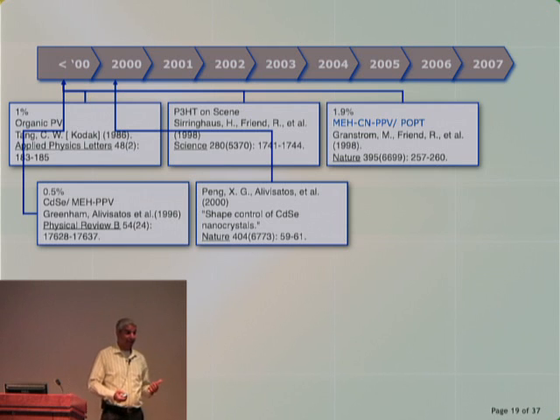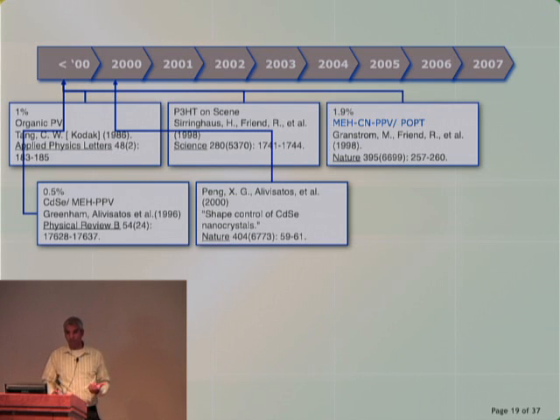Wouldn't that actually produce more photocurrent or a better charge mobility than in just the all polymer? And what you see is some very modest efficiencies, 0.5%, which kind of paled in comparison to the 1 to 2% that they were already achieving in all polymers. So this group, the group that I've been part of, worked then mostly on shape control of these nanoparticles.